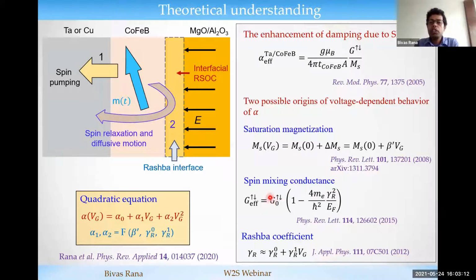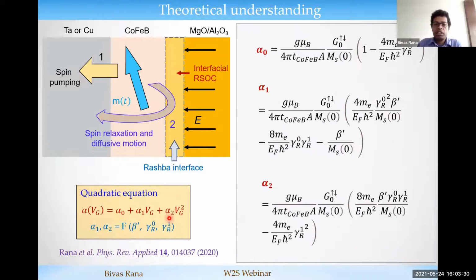That means the total spin mixing conductance is no longer independent of the gate voltage, but can be expressed by this expression, where gamma R is the Rashba coefficient, which is essentially linearly proportional to the gate voltage. So if you plug all this into this equation, you will end up with this quadratic equation, where alpha 0, alpha 1, alpha 2 can be expressed like this.